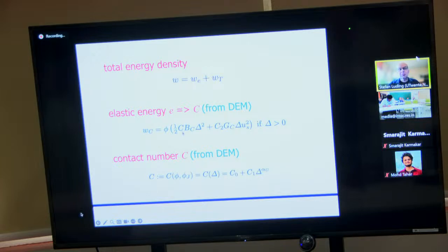Good. C stands for contact number or coordination number, or however you call it. And in the theory, it can be expressed as a nonlinear function with 3 coefficients, where alpha c is 0.5, delta is the elastic strain. So it's a relatively simple function which matches with the particle simulation data. So this is again the things which I added to the GSH theory because I know those things from my own particle simulations. So I intrinsically believe it.